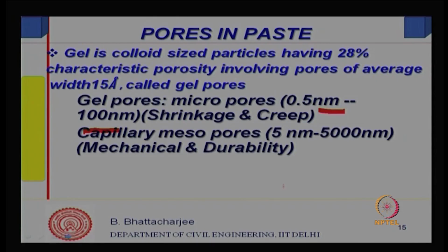Capillary pores are slightly larger, called mesopores, and the size would be 5 nanometer to 5000 nanometer. They are responsible for mechanical strength, that means load carrying capacity, and durability properties of the cement paste and then concrete.